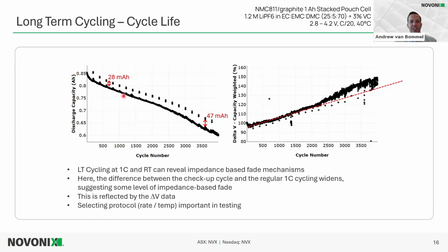But we see this 1C cycling, and we notice that at the beginning, the difference between RPT and the normal cycling is 28 milliamp hour. And then as we proceed to cycle 3600, it's 47 milliamp hour. So this is strong evidence of some impedance-based fade mechanisms occurring. And if we look at the delta V, which I'll talk about in the next slides as well, the delta V also increases a bit at that same cycle. So at some point, we see evidence of impedance-based fade at this level.